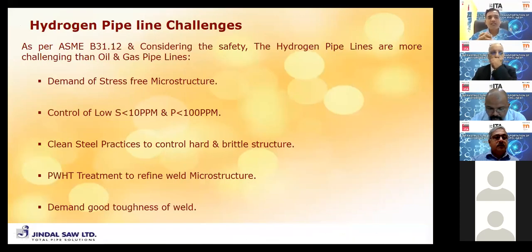So what is the challenge? Actually, the currently available standard is ASME B31.12, which covers the safety and the challenges of hydrogen. What a hydrogen pipeline demands is that the structure must be free of any detrimental effect. The sulfur must be controlled to less than 10 ppm, and if we weld it, it requires a uniform microstructure that may need PWHT, post-weld heat treatment, and it also demands good toughness. Next, please.